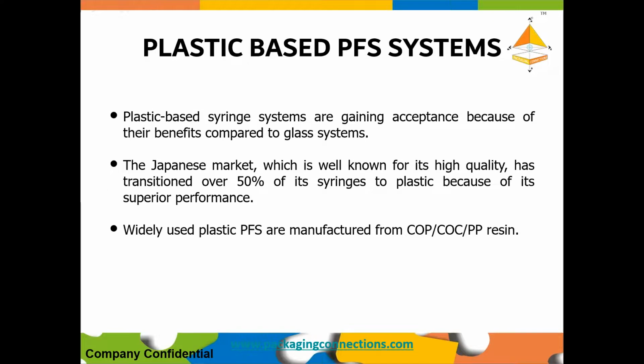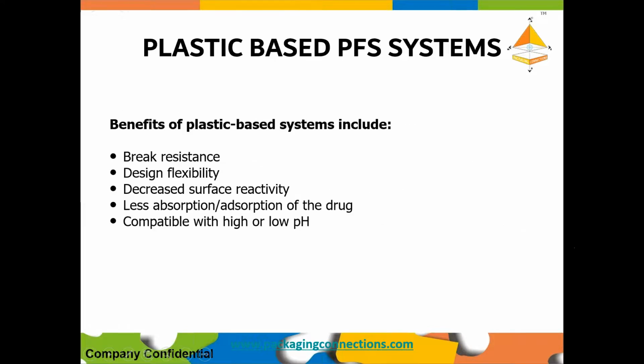When you move to plastic-based, that's the reason plastics are becoming more and more popular now. I understand that Japan is almost 50% or more with plastic. Widely used, as I mentioned before, are COC, COP, PP, and some others. Benefits: break resistance, much bigger design flexibility because it's injection molded, so you have better control on the dimensions. Surface reactivity is also minimized, and absorption of the drug is also less. And plastics are generally compatible with high or low pH equally.